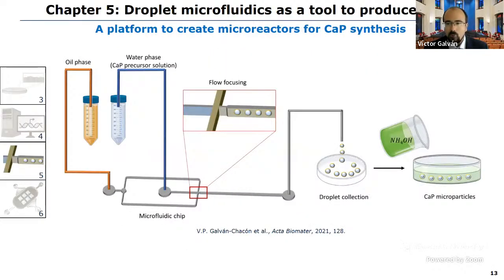In the next chapter, we moved from obtaining knowledge about calcium phosphate to producing calcium phosphate microparticles. The way we did that was to create microfluidic chips able to produce droplets loaded with the calcium phosphate precursors. When these droplets were immersed in ammonia, the calcium phosphate microparticles would precipitate. The reason for doing this is that the droplets produced in this kind of devices are totally homogeneous, and therefore each of them acts as a microreactor. And the resulting materials are extremely homogeneous as well.